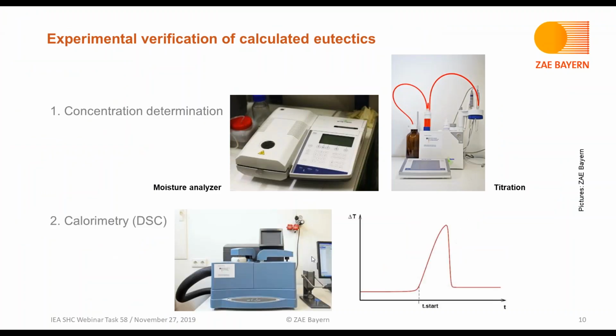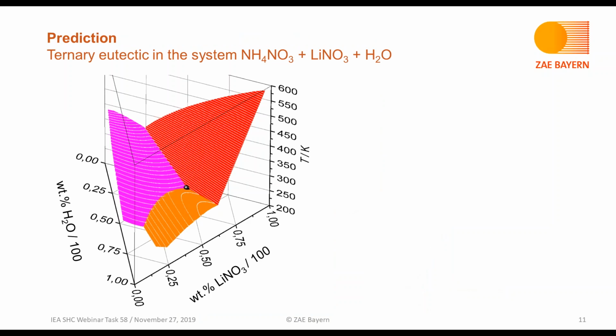Okay, so now we can go on. The second step is to perform calorimetric measurements. Therefore, we're using a DSC, differential scanning calorimetry. To explain it in a bit more detail, I'll give you a brief and rather simple example. Here it's the ternary system containing ammonium nitrate, lithium nitrate, and water. Shown on the left is the phase diagram, the three solid phases that occur here, and indicated as a black ball is the location of the ternary eutectic.